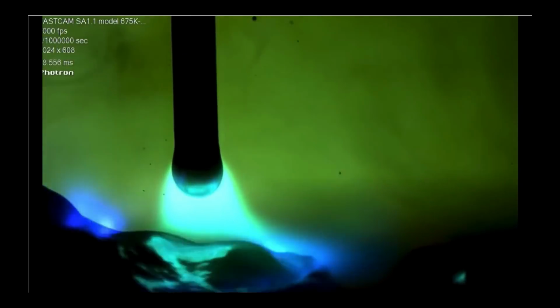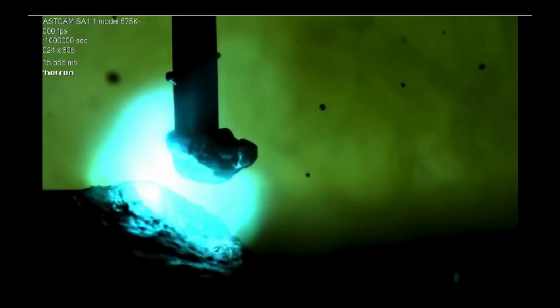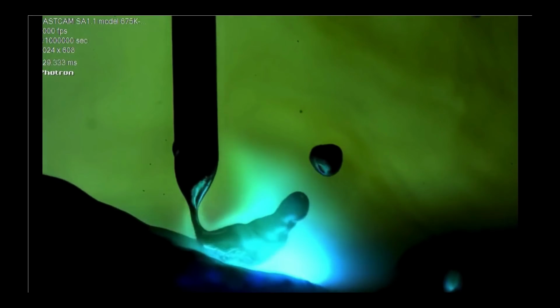Well, if you look at arc welding very, very close up, this is the electrode, what happens is it melts the steel of the electrode, and the two things kind of splash together with the arcing of the electricity, causing this reaction. And it splatters off these tiny little drops. You see this huge spray of tiny little drops of steel there. Those will all solidify in the air and turn into iron microspheres. And this video is running at 1/300th of normal speed. So at real speed, there's basically this constant stream of iron microspheres.